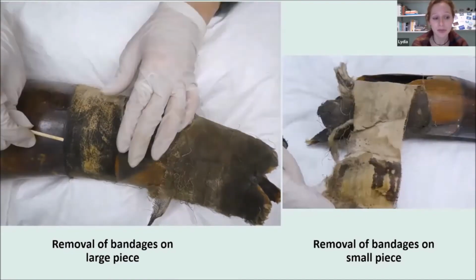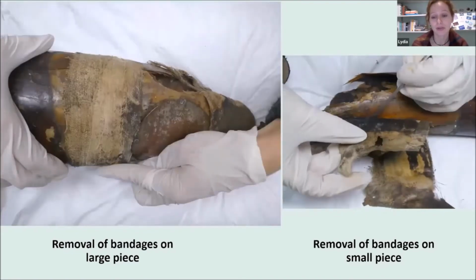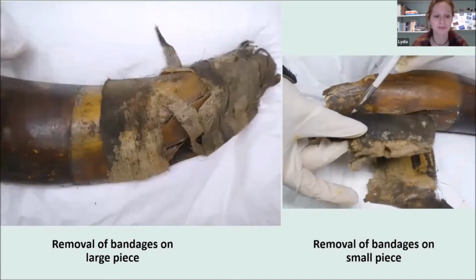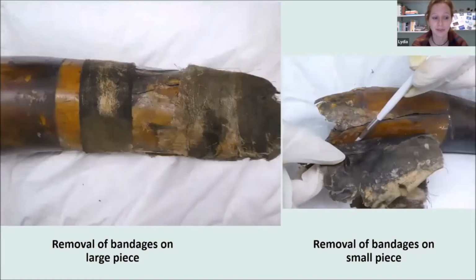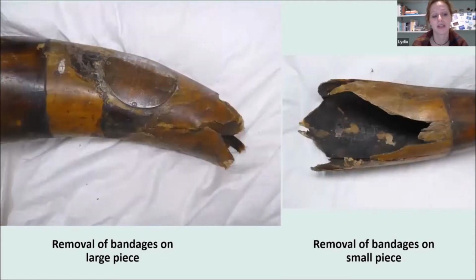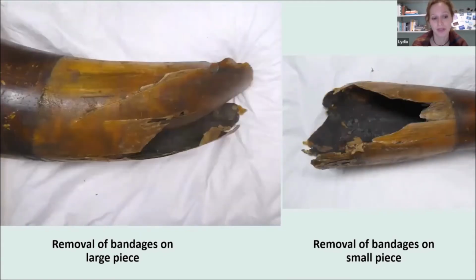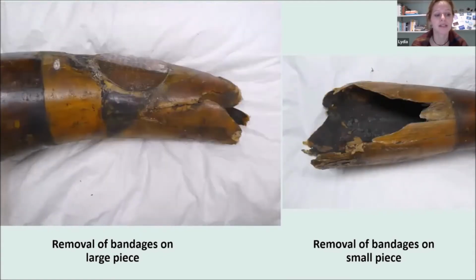During the unraveling process, I gained new information about the repair itself. 3 different types of fabric had been used and adhered with protein glue. I also became aware that the dark brown coating on the surface must have been applied after the bandaging, as it was not found underneath, but instead stained the top layers of these bandages.